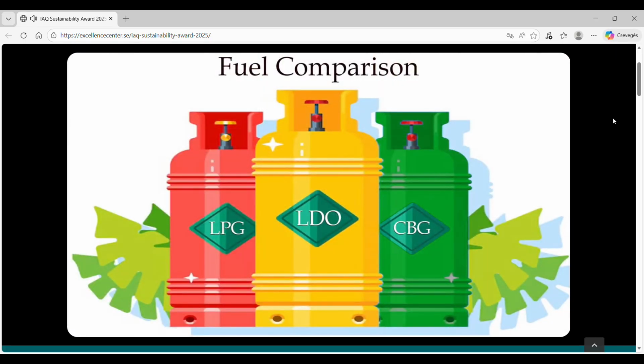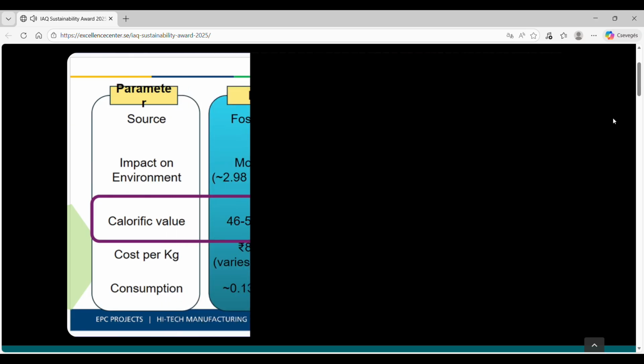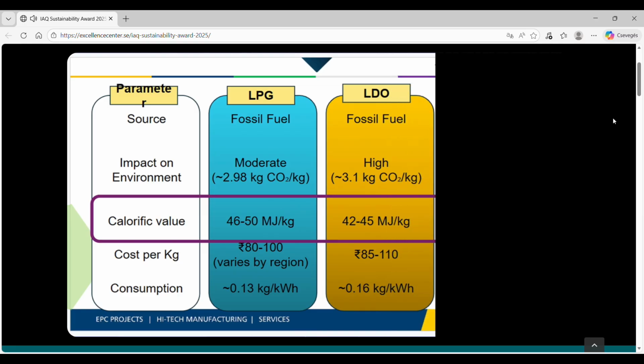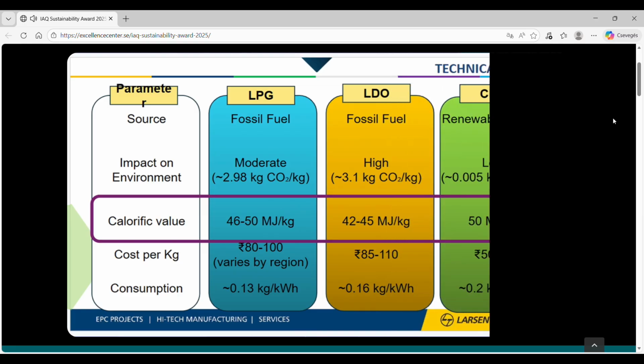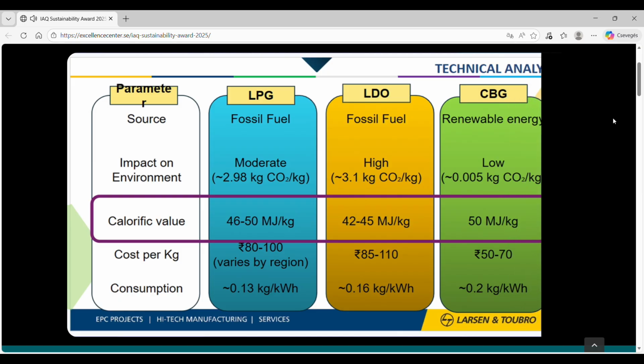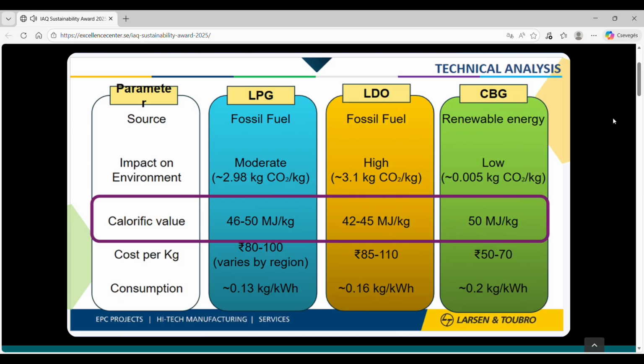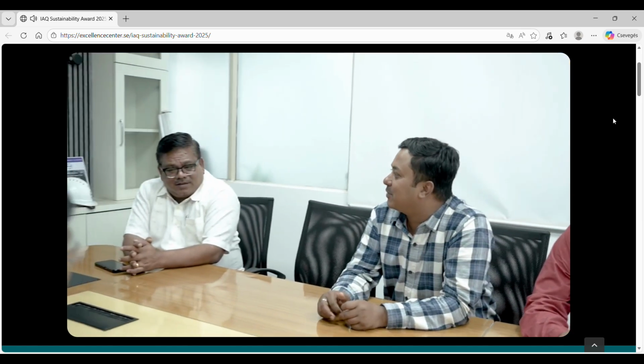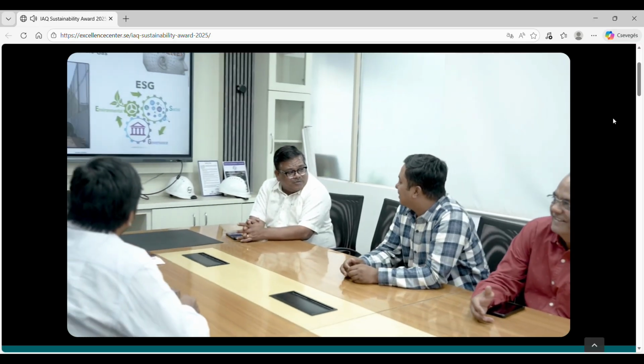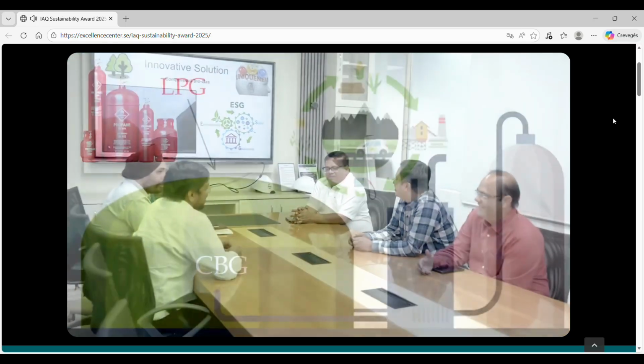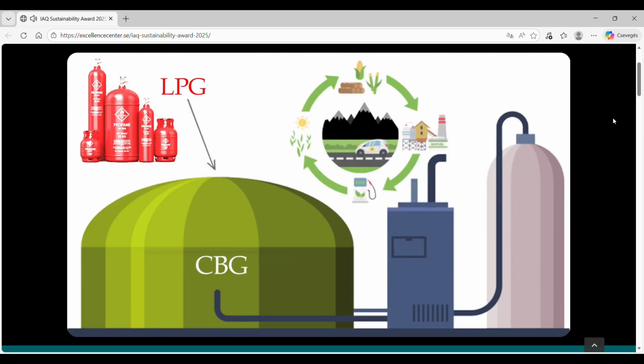We evaluated alternative fuels. LPG emits 2.98 kilograms of CO2 per kilogram of fuel. LDO emits 3.1 kilograms. But compressed biogas emits only 0.005 kilograms, making it almost carbon neutral. And with a calorific value equal to LPG, CBG became our preferred alternative. With detailed analysis and quality-driven brainstorming, we decided to transition our galvanizing furnace from LPG to CBG.